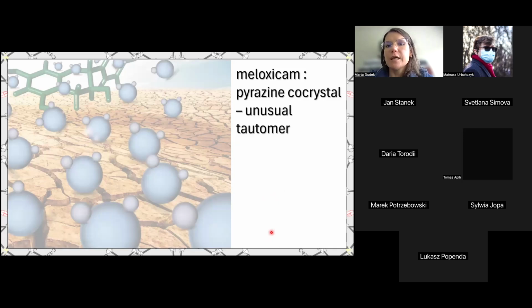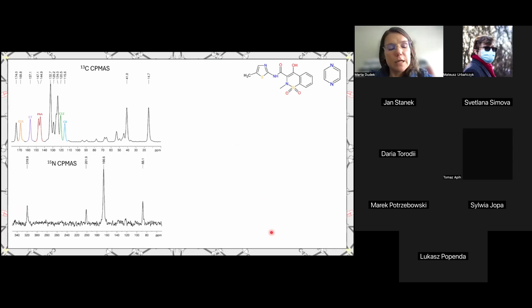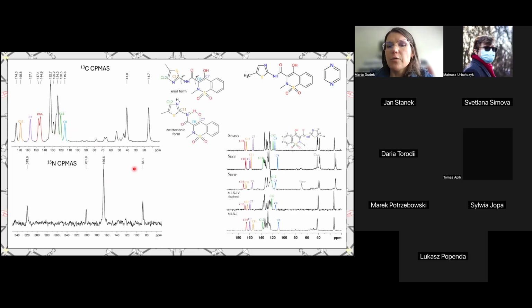So now briefly about the second system, we studied meloxicam with pyrazine. In this case, we did not have any crystal structure from single crystal X-ray diffraction. When we registered solid state NMR parameters, we saw that the order of the chemical shift resonances should correspond to a Zwitter ionic form of meloxicam. This comes from our earlier studies. Meloxicam can easily exist in its enol form in crystal structures, but there can be a proton reordering in this structure, and it can exist in Zwitter ionic form.